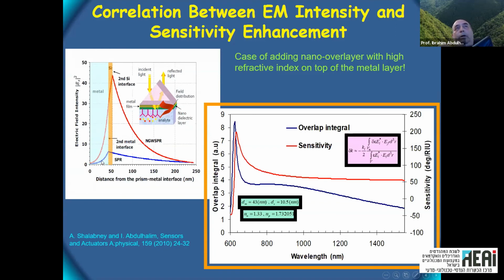So if we calculate the field for the standard SPR without the silicon layer, we get this one. As you add the silicon layer, you get here a factor of almost 10 in the intensity of the field. And this also improved the sensitivity. So that's how we arrived at this correlation between the two.